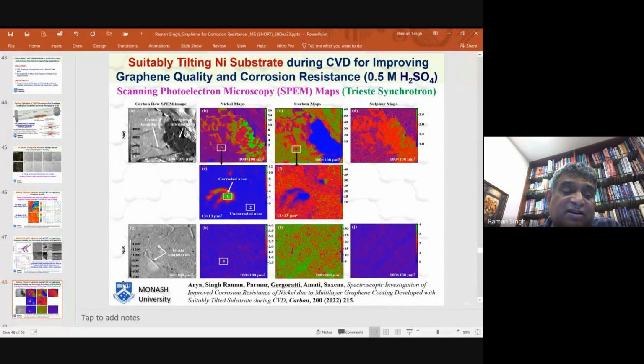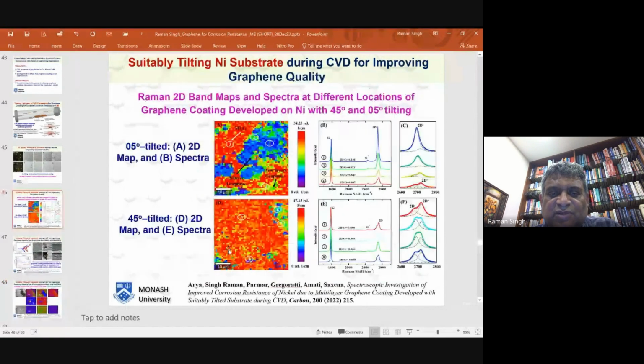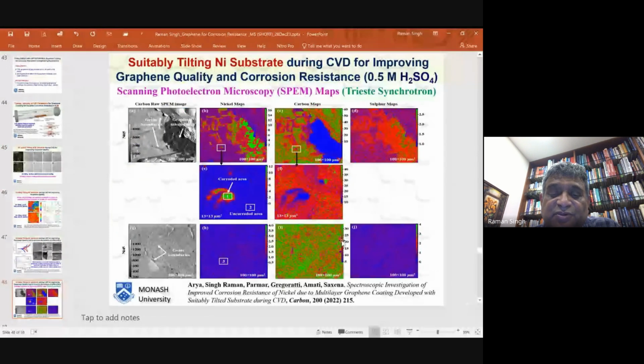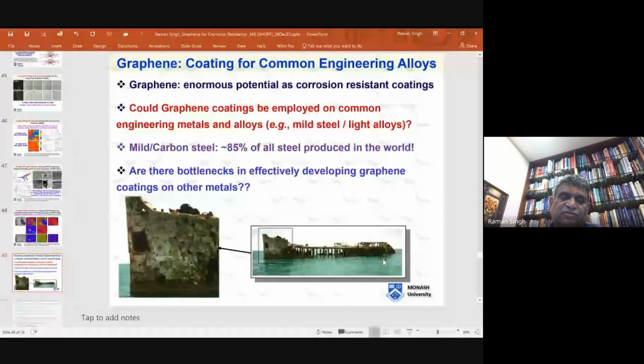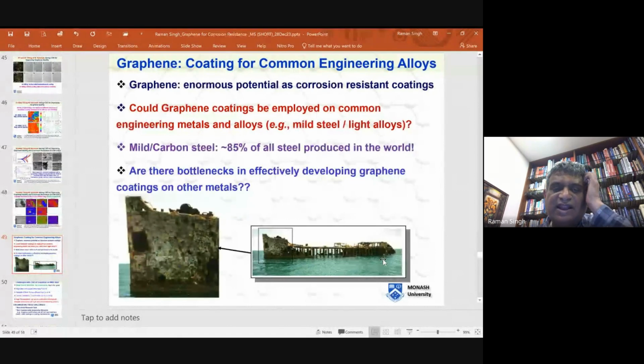As opposed to that, the 45-degree tilted sample did not show any nickel at all. There was not much disruption, as you saw earlier, on the surface. And there is a beautiful uniform carbon signal across the entire surface, and also there is no sulfur signal, meaning there was not much attack. I come to the last part of my talk.